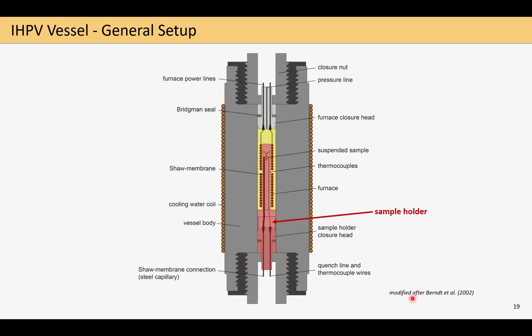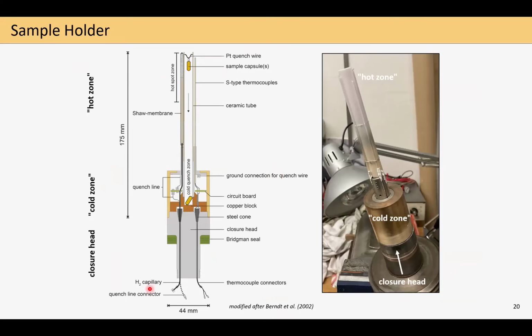And then the last main component of our vessel is the so-called sample holder, which in the end just serves us to bring our samples into the hot zone of the furnace. And this is inserted from the lowermost part. And here again, a schematic cross-section or overview of such a sample holder, where we can distinguish three different zones or parts.